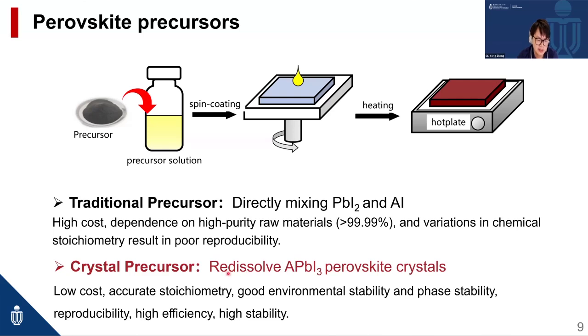By using this method, we can synthesize these precursors starting from very low cost raw materials and lower the resulting precursor cost, and then control the accurate stoichiometric ratio in the resulting precursor to achieve higher reproducibility and high efficiency solar cells. We can also synthesize environmentally stable precursors to have good storage stability and phase stability.